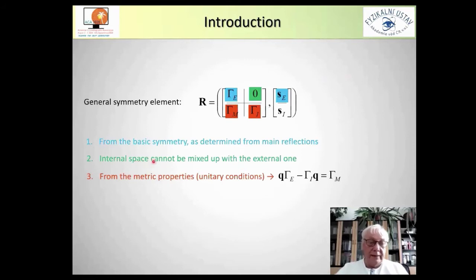Second point, internal space cannot be mixed with external one, because this artificial vector which we introduce is perpendicular to our space and cannot be moved from this superspace to real space, which means that these columns are equal to 0. So this makes a big reduction of these properties. And something more, from properties of modulation vector, we can find this special equation which makes a relationship between modulation vector and this gamma E, gamma I, gamma M. This allows us to fully determine this matrix which is used for symmetry.